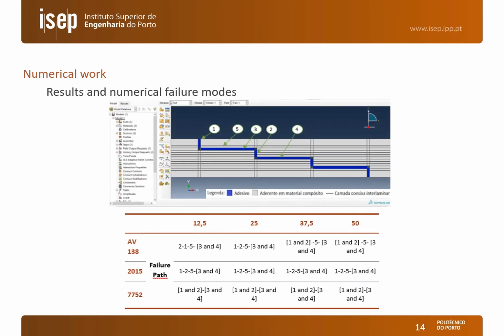Beginning with the numerical results, here we can see the different failure possibilities that were introduced in the model. Location 1 and 2 are the butt portions of the step lap joints, 1 at the edges and 2 in the middle step. 3 represents the outer steps, and 4 the inner step. And finally, location 5 is the interlaminar failure of the composite.